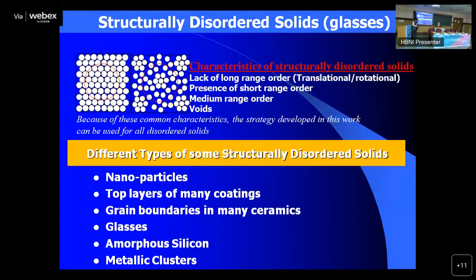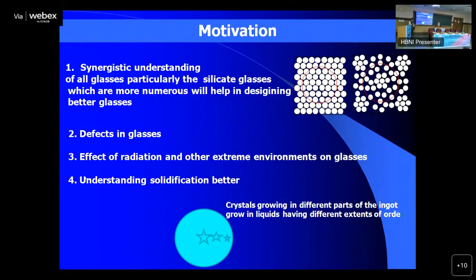Some of the disordered solids that we know of are listed here: nanoparticles, top layers of many coatings, grain boundaries of many ceramics, glasses, amorphous silicon, metallic clusters, and so on. This list is much larger. I have only given a few here. And what is the motivation for studying this? The motivation is, if you study one, you develop the pathway for studying all of them. Study metallic glass, and you will know how to study non-metallic glass, which is actually around us in very large tonnage and has been there for centuries. Still, the structure is not known.